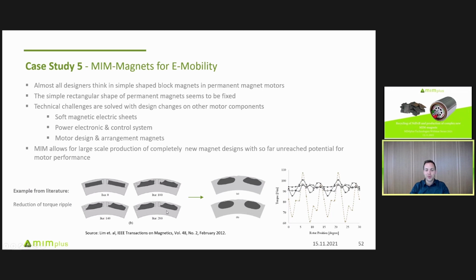They said, okay, nobody can produce that so far. How can we make it so that it can at least be produced a bit by pressing and sintering, and they got to that shape. But it's impossible to produce that on a larger scale with pressing and sintering. But these geometries could be ideal for the metal injection molding technology. And with this optimization, you see here, it's a green yellowish line. It's the torque rippling at the beginning of iteration 0. And these blackish lines are nearly without torque rippling after optimization of the shape.